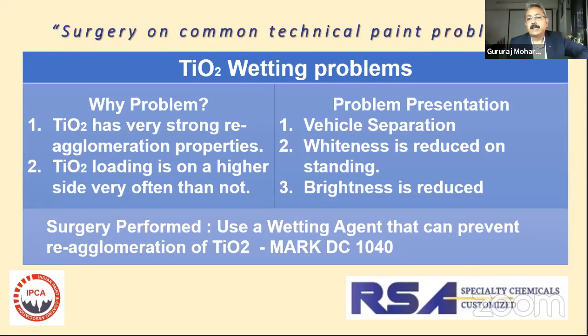Yes, titanium, as they say, is like a cow, we can easily turn it our way. That is right, it is not completely wrong, not completely right either. Titanium is a pretty easy pigment, one of the easiest pigments to grind. It gets wetted very easily. It goes into the system very easily, whichever system, water-based, solvent-based, your industrial epoxies, titanium does go in very easily.